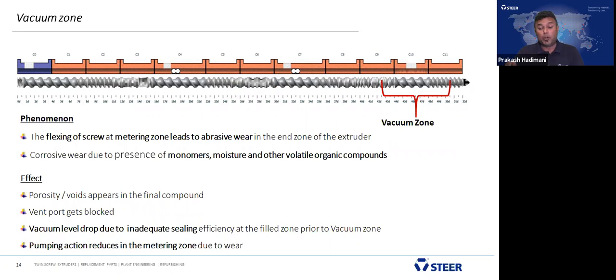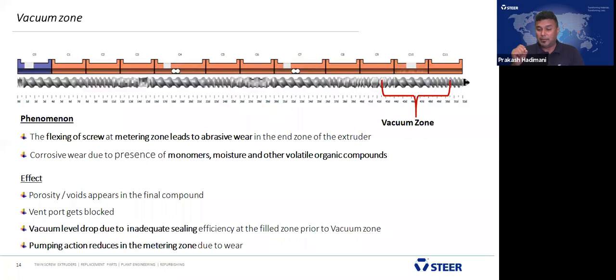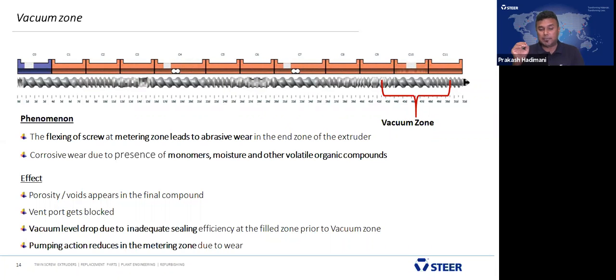Now, the important zone is the vacuum zone, because this phenomenon contributes to both the vacuum and the metering zone. Here, the flexing of the screw in the metering section leads to abrasive wear in the end zone of the extruder, because material starts to stagnate there and flexes the screw. Okay, that's in the metering zone. And it also forms corrosive wear due to the presence of monomer, moisture, and other volatile organic compounds.